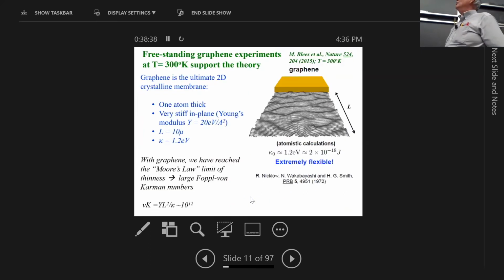The experiments at Cornell did something which is really cool. They used a cantilever experiment to measure the bending rigidity of graphene ribbons of varying length. And this is what they noticed. If you put in 10 micron width for this thing, 40,000 times wider than it is thin, you've reached the Moore's law limit of thinness with these freestanding graphene ribbons. You ain't gonna get anything thinner than that.